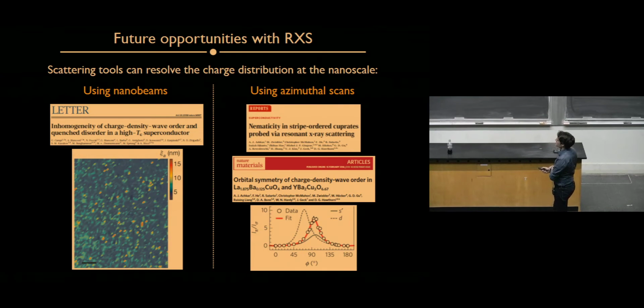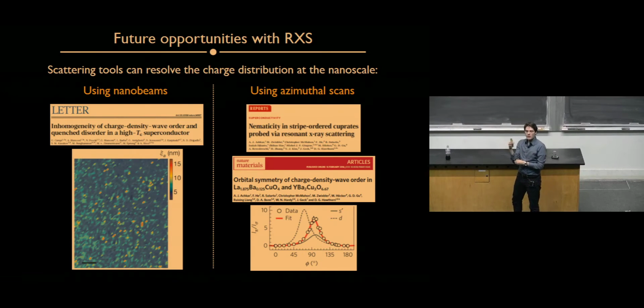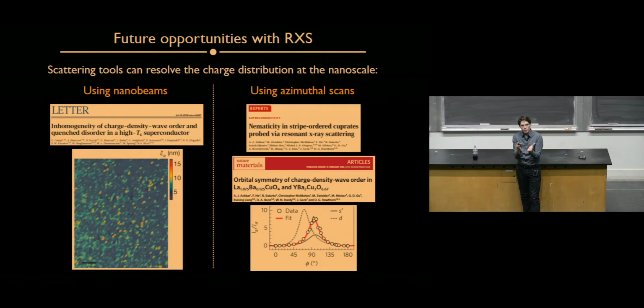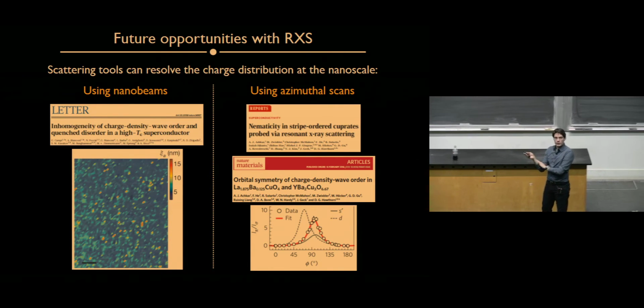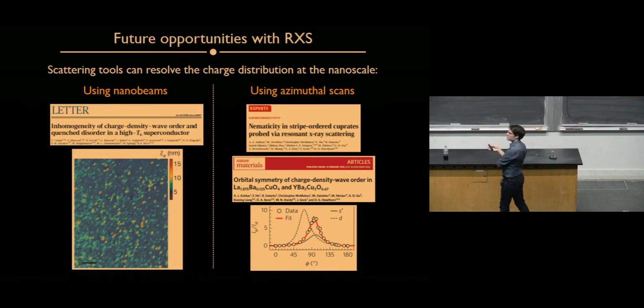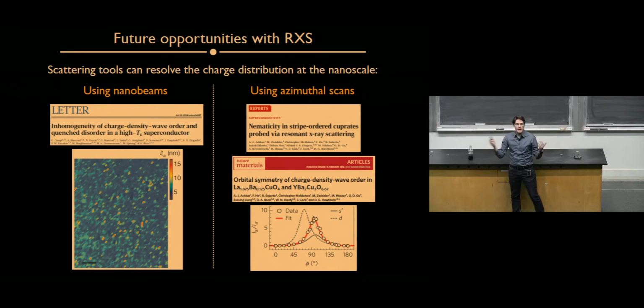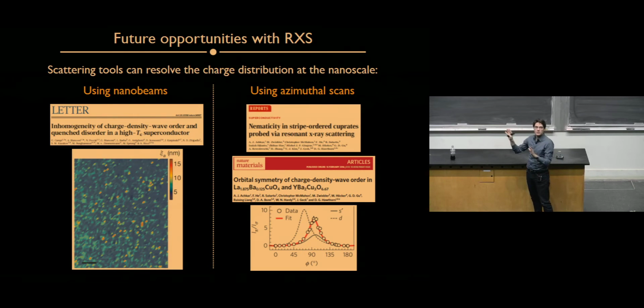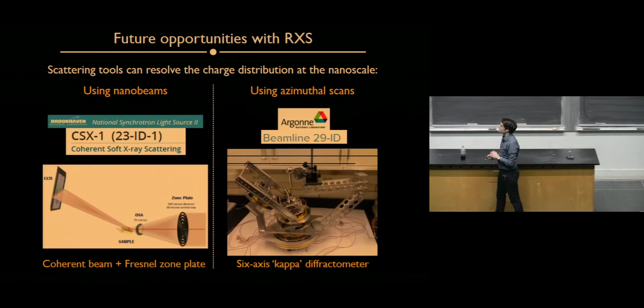And the other possibility is that of doing what I was showing before, so using these azimuthal scans by scanning the polarization around, but now with the added capability of also projecting the outgoing polarization to get an even better understanding of the local orbital symmetry of these ordered states in these quantum materials, not just cuprates, but now we're exploring nickelates, we're looking at manganites. So we're using these new tools to look back at materials that had been studied previously, but not with the experimental suite that we have right now.